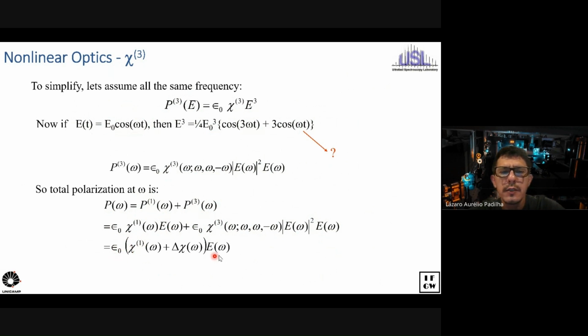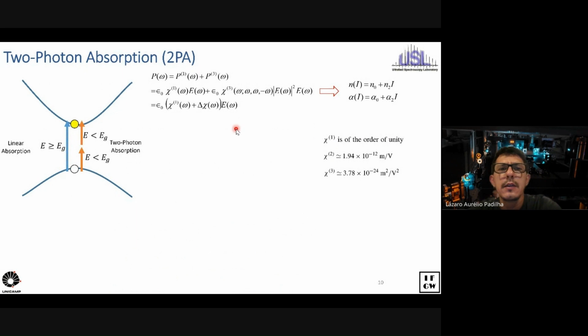And we can rearrange this and call this chi1 and call all this a delta chi. So this is a perturbation to chi. And this refers to the linear absorption and refraction. Meanwhile, this corresponds to what I call nonlinear refraction and nonlinear absorption. In fact, if you write down the math, you're going to realize that the real part of chi1 is proportional to the refractive index, and the imaginary part of chi1 is proportional to the absorption coefficient.